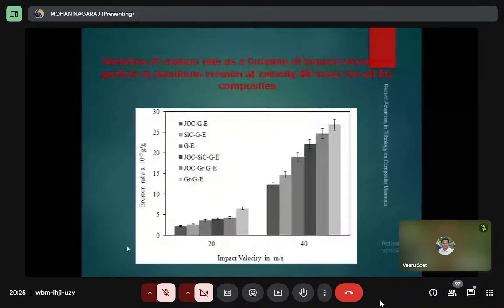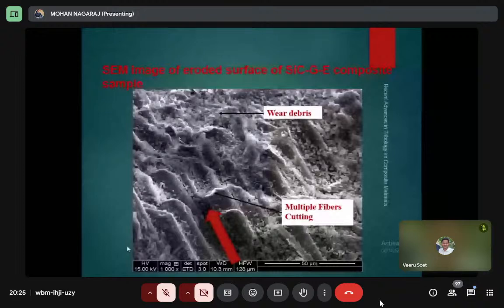Here also we observed the JOC filled glass epoxy composite. Again, in the SEM images of the impact, in the Jatropha oil cake filled glass composite, fiber breaks and matrix damage with JOC 25 are less than in the other composites. Here we observed more eroded surfaces in the silicon carbide glass epoxy composite samples.